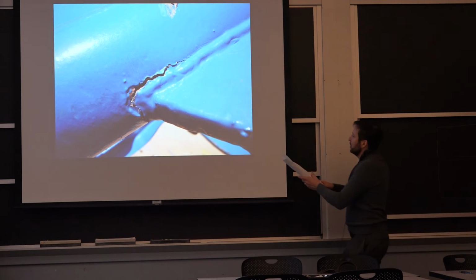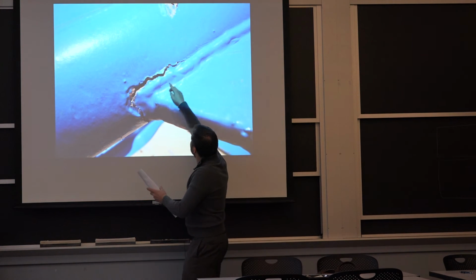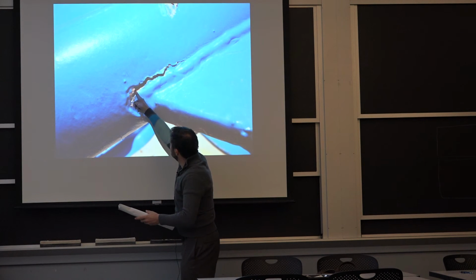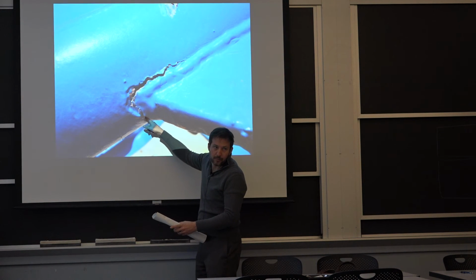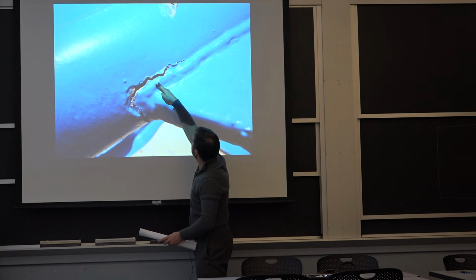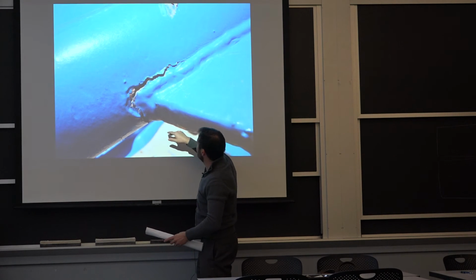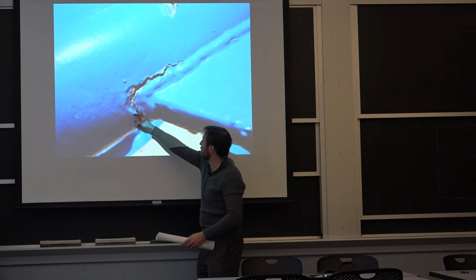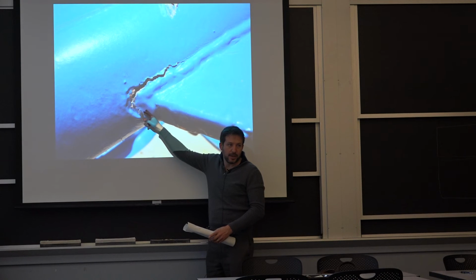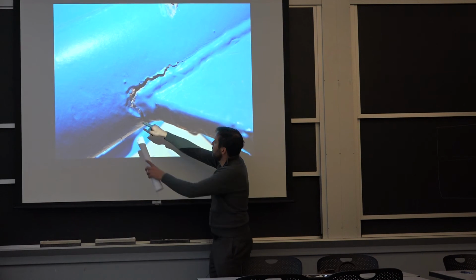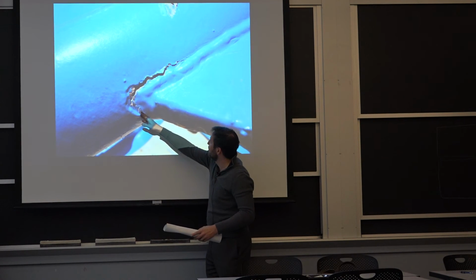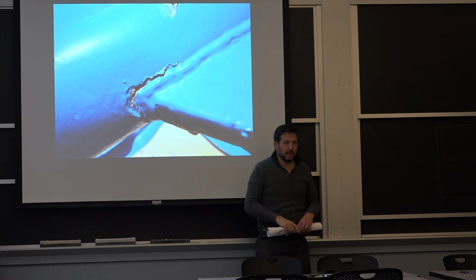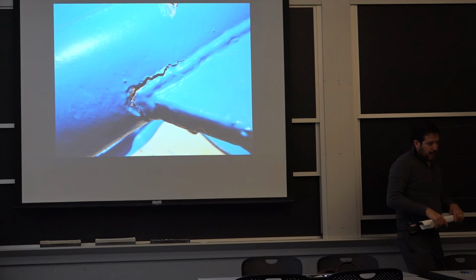So over here we're looking, we have the gusset going on. This is the notch. So you want to make the notch bigger and not fill it in with a filler metal. So you should have stopped right here and right there, because what happened here, it started to crack right there in the tension zone where the loading is this way, it was perpendicular, and then of course it started to propagate in different directions.